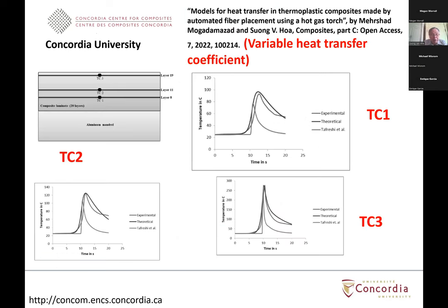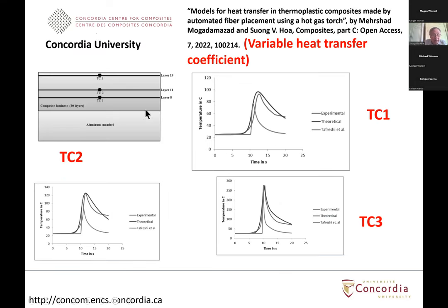So a few years ago, we took the effort of trying to do the analysis and take into account the variable heat transfer coefficient. In this case, we were comparing the analysis at three different points inside the laminate, at layer 8, layer 11, and also at the top surface. And this one shows you one example of the analysis for the case where you have the constant heat transfer coefficient and the variable heat transfer coefficient, compared to the experimental result. You can see that if you use a constant heat transfer coefficient, there is a big difference between that and the experimental result. When you use a variable heat transfer coefficient, you have better agreement. And this is shown for the three different locations. So this shows that some work needs to be done to make sure that we have good data to enter into the model that we use.